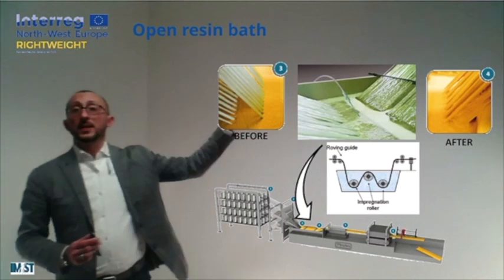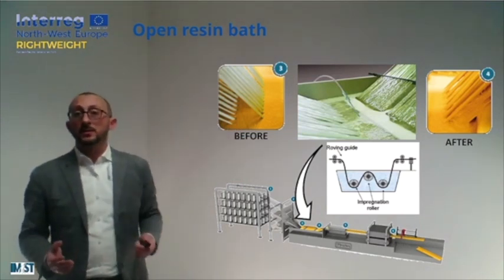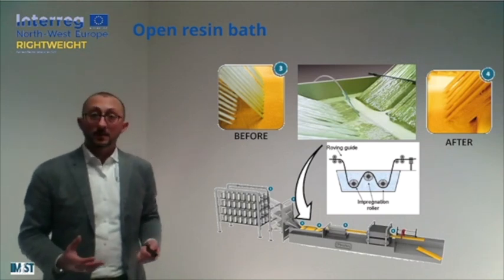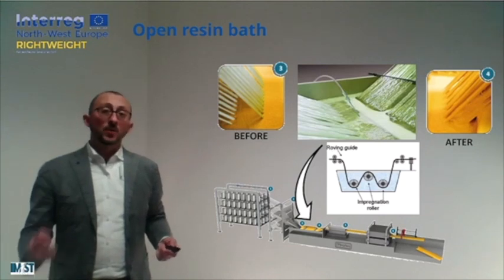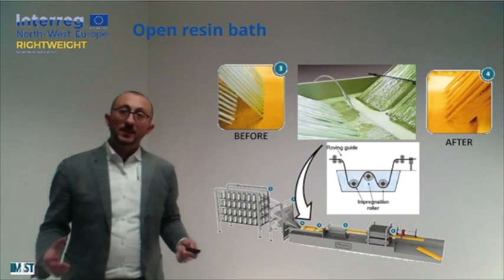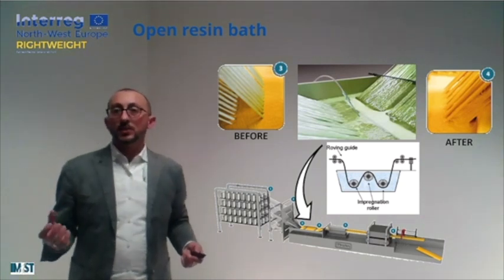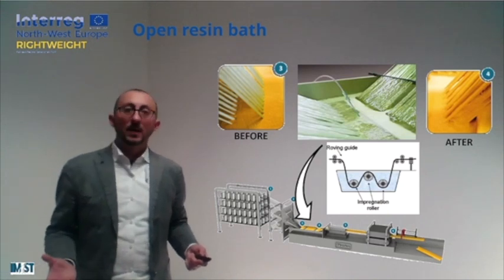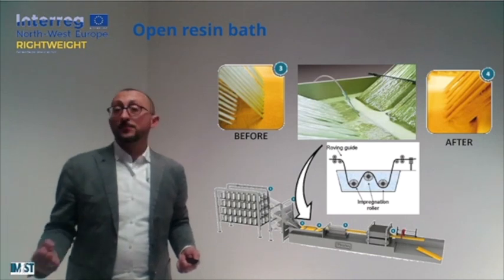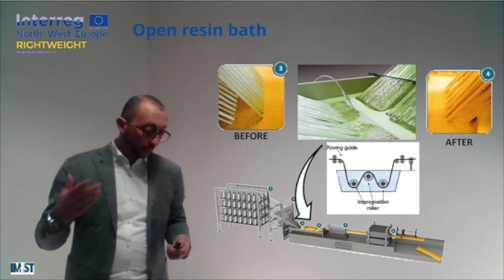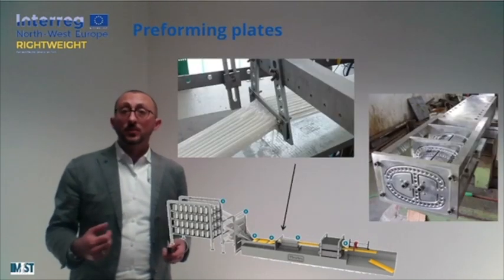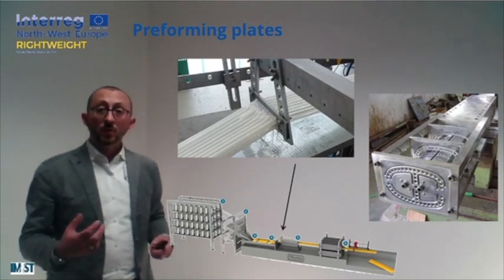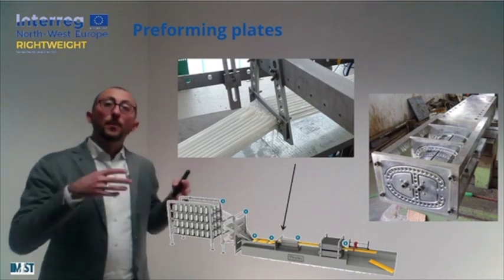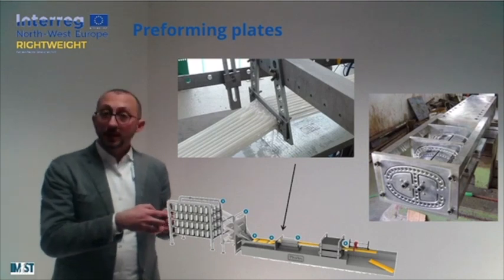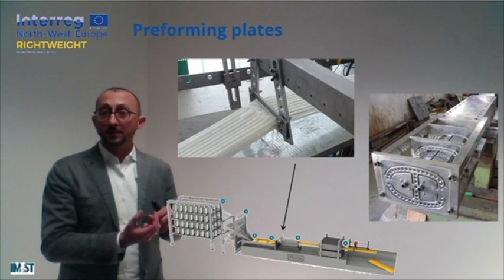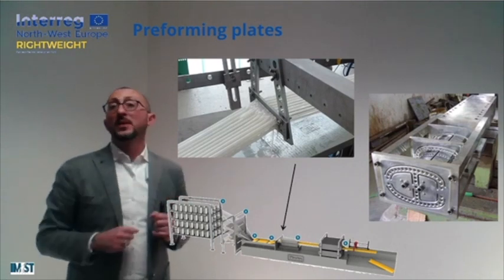Now, looking at the picture over there, where the situation of the reinforcement and resin after the bath is depicted, you can easily see that when we are going out from the resin bath, the amount of resin that is surrounding each tow is generally much more than the resin that we need in our composite cross-section. And for this reason, after the open bath, some other tooling is used in order to, first of all, remove this excess of resin and also to force this surrounding resin to penetrate inside each tow in order to completely wet also the fibers that are at the core of each tow.